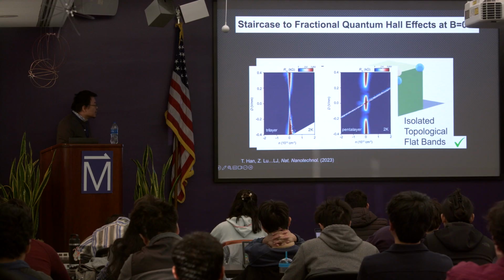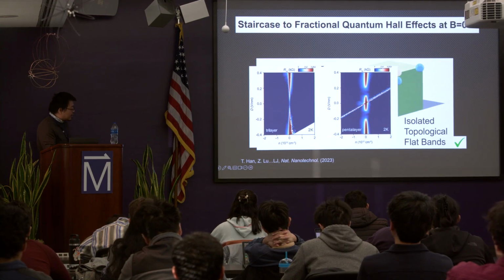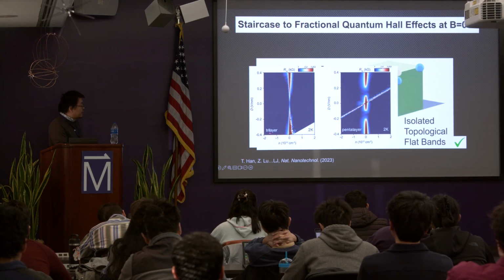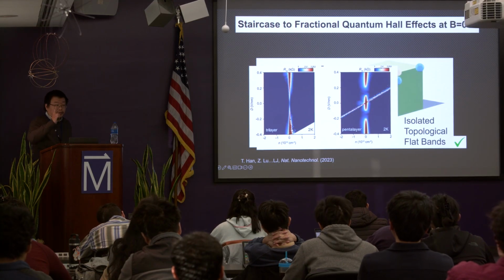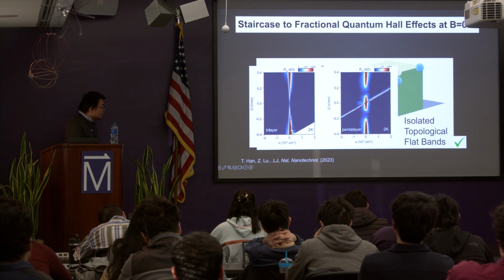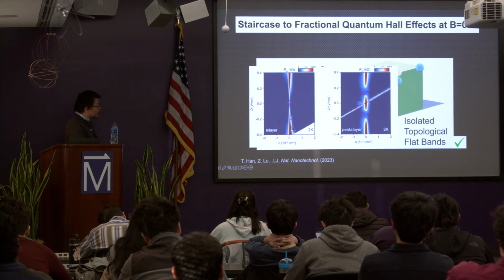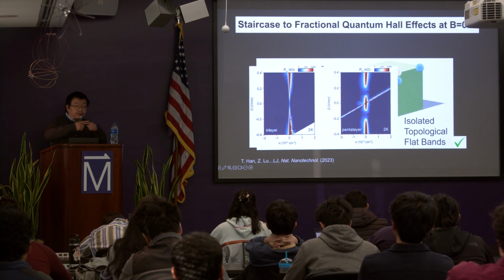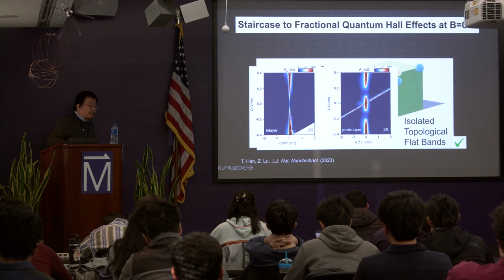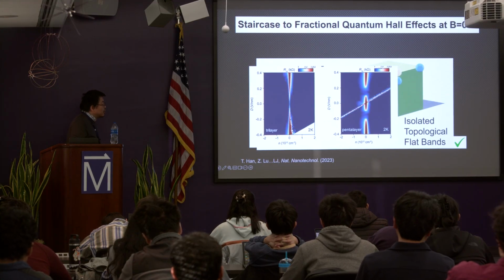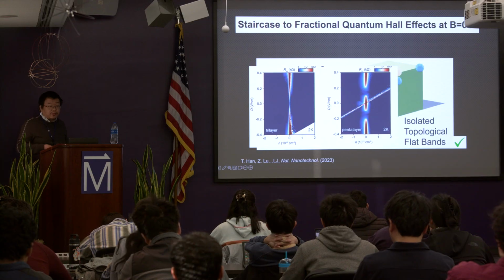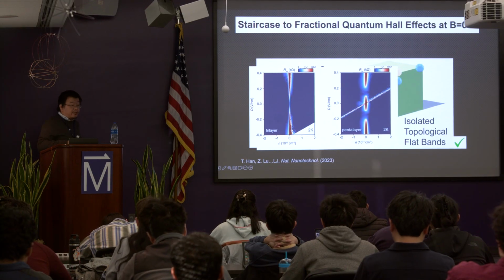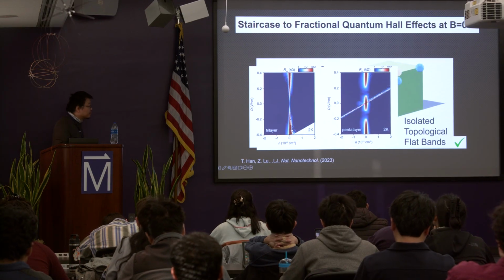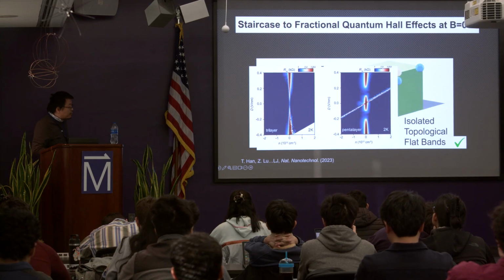For example, this is a trilayer graphene. The horizontal axis is how much you dope, the doped electron or doped hole, and the vertical axis is the electric field you add across the sample. So at zero doping and zero displacement field, you should have the band crossing there, and you should expect something like metallic behavior, right? Which should also be true for thicker layers, right? So you also have a lot of density of states here, which should be a good metal.